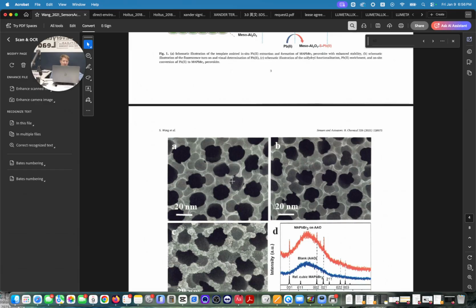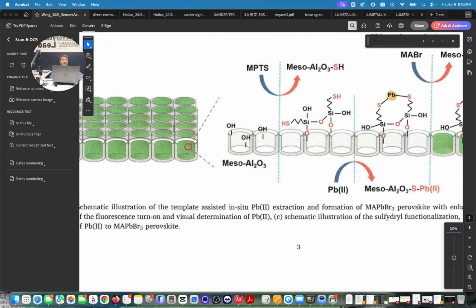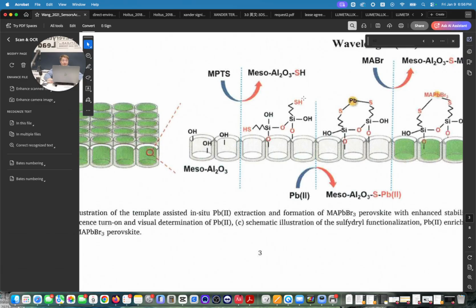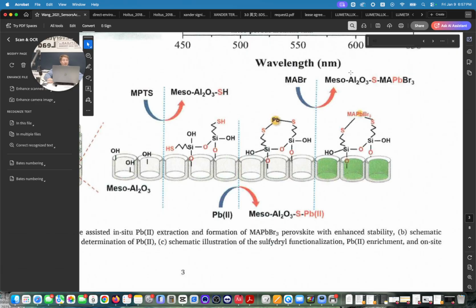This is microscopic. And they actually found that you can't get any lead to stick to the surface until you add something called MPTS. And this is something that I've worked with. It smells like sulfur, and it makes me feel sick. I did this experiment several years ago in my kitchen. That was regrettable. But I was able to replicate it, and it is pretty interesting because it has the distinct ability to latch onto lead. And so you can see here that the functionalization of the surface basically is composed of these sulfhydryl bonds attaching to the surface. And then we have lead, right, being captured. And then we have lead being converted with methylammonium bromide into a perovskite, which can be seen.